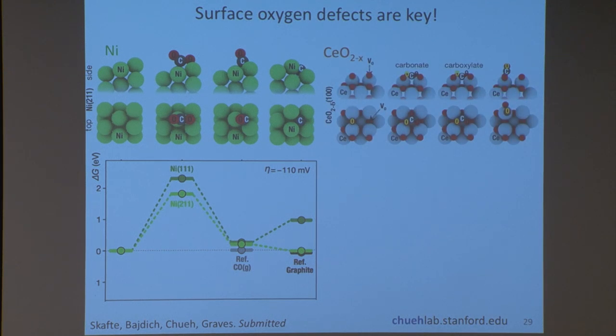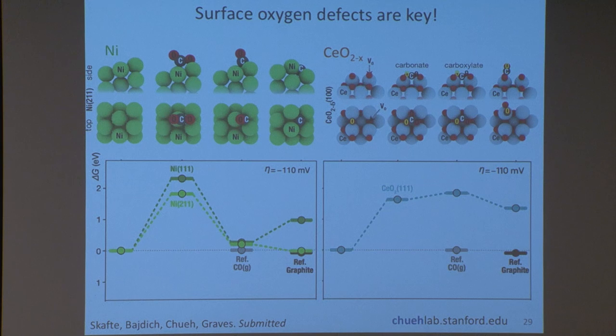What we wanted to figure out is why the additive of cerium oxide makes it so much better. So we then computed what happens on a cerium oxide surface. Okay, so same process, starting with CO2, and then stepwise removing oxygen from CO2 to CO to carbon. The first plot here shows you the energy landscape if no oxygen was missing from the surface. So this is the perfectly ideal material, no defects. You can see the energy pathway actually looks quite different than nickel already. So you still have very unfavorable CO2 adsorption, but you also have very unfavorable CO adsorption. But the bonus is that your energy is quite high for your carbon intermediate.